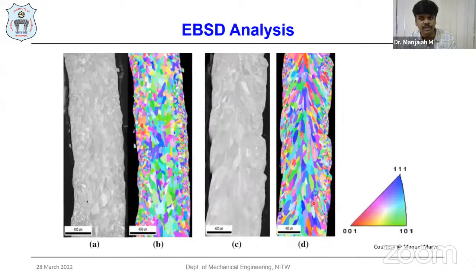And if you see, EBSD analysis shows us the grain orientation as well as the grain structure and grain sizes, with respect to the build direction and the horizontal direction. If you see, this is the build direction, and this is with respect to the horizontal direction. And what is the grain orientation, whether it is in the 111 plane, 001 plane, or 101 plane in the fabricated conditions.